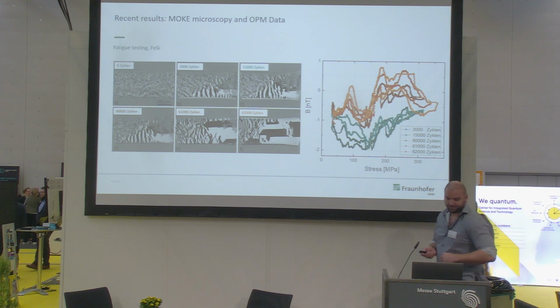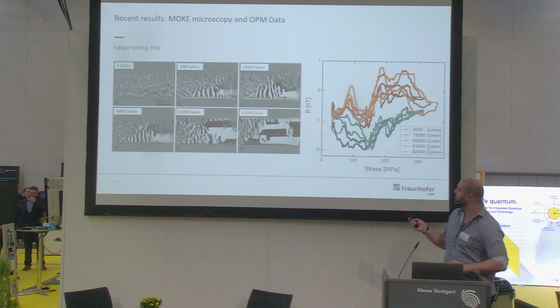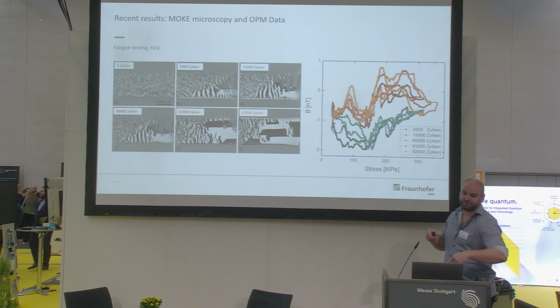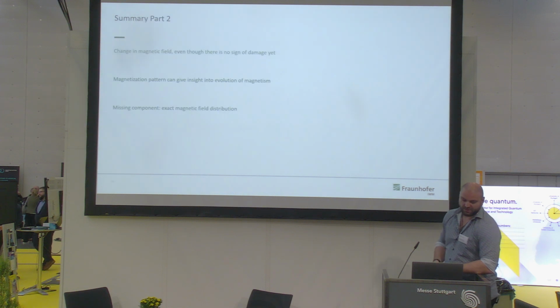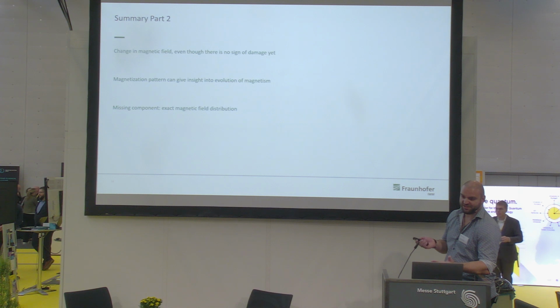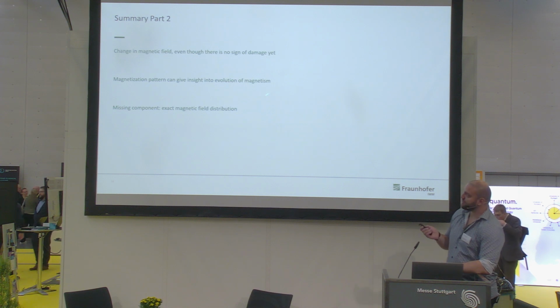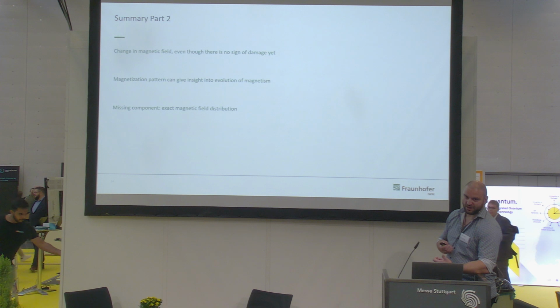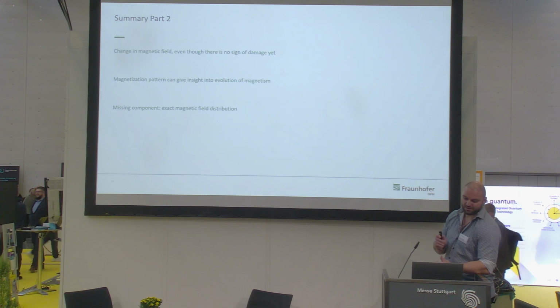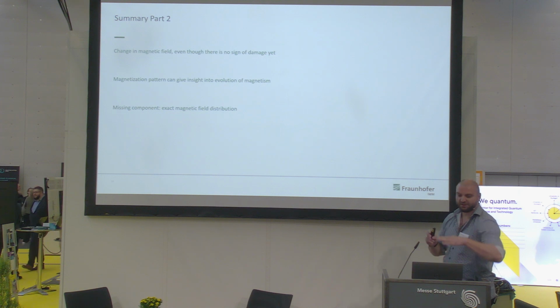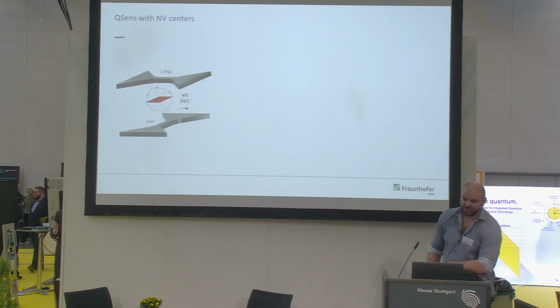So this gives us the information that the magnetic field in the OPM holds information about the structure of the material before we can see it in the microscope. Let me summarize. First, we have the change in magnetic field even though there is no damage seen yet in the material. We have a magnetization pattern, which gives insight on how the material is damaged, where we get the pinning. But we have one missing component, because in the MOKE we only see the surface qualitatively, and we get in the OPM a signal from the whole sample. So we have to bridge that gap, and we do this with quantum sensing with NV centers.